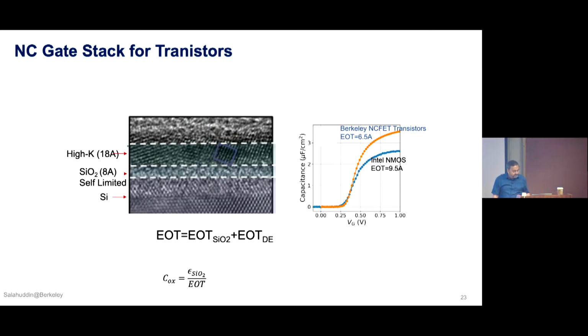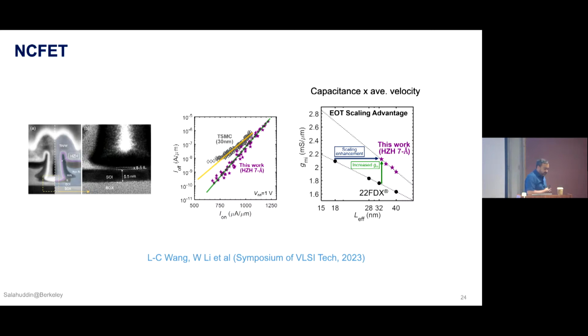Okay, so what does this extra capacitance give us? Here are some results on 30 nanometer channel length transistors that we built here at Berkeley. This is I-on-I-off directly measured for a VDD of 1 volt, compared to some published data for similar channel length transistors from TSMC. You can see that our on current is larger and off current is smaller. And this is despite the fact that our source drain resistance is much worse than what TSMC can do. This is a university made transistor, and still there is no projection here. This is directly head-to-head measurement.